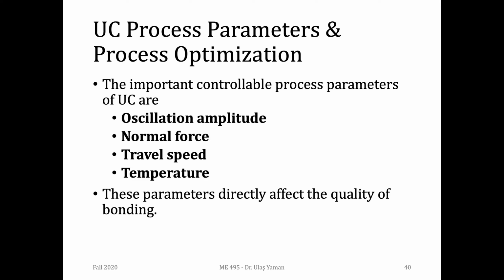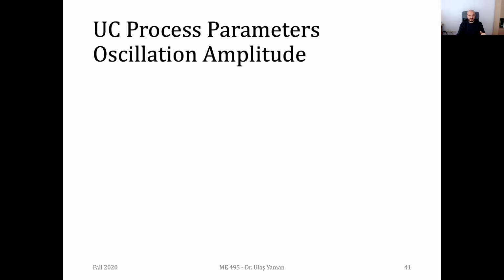Layers will not bond, but if the force is too much, it will deform and harm the product. Yep, you're exactly right. So we need to find an optimal force value. If you have too much force, the surface quality will suffer and the surface roughness will be higher. In the next layer, that high surface roughness will not let you join the new sheet metal to the previous one. So these parameters should all be optimized to have a perfect bond between the layers.